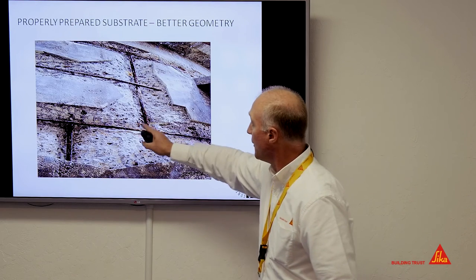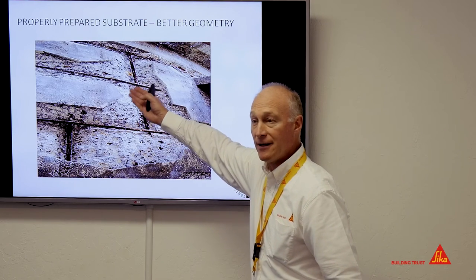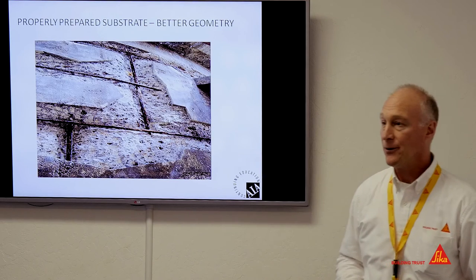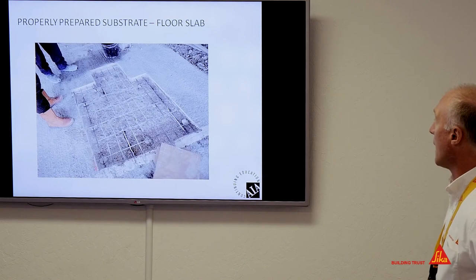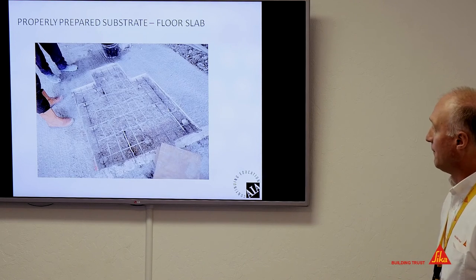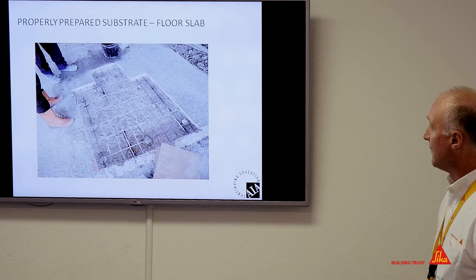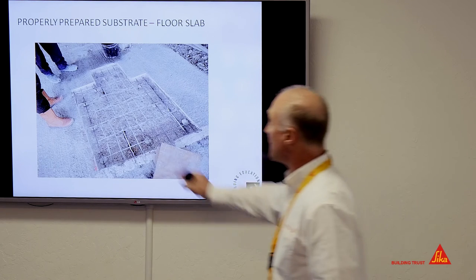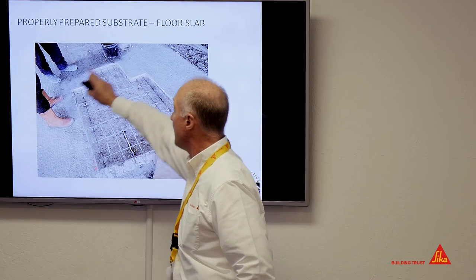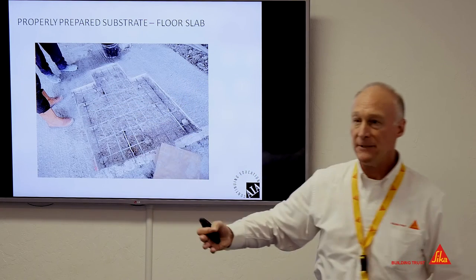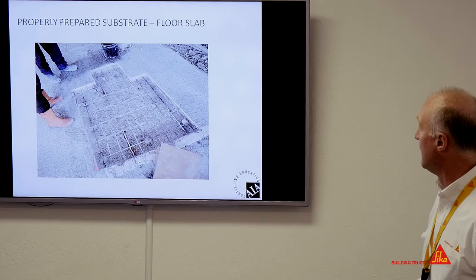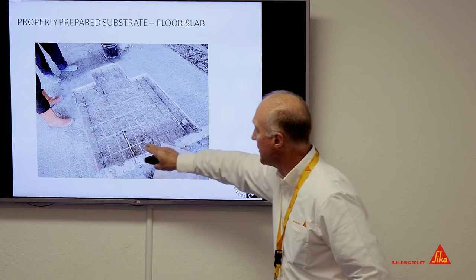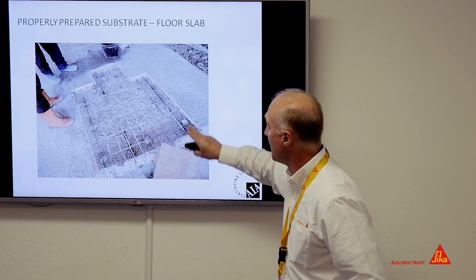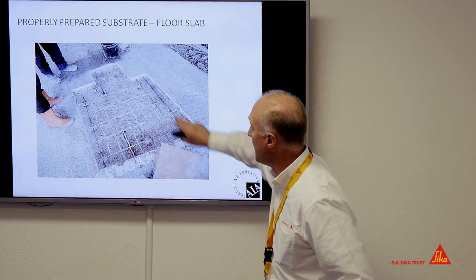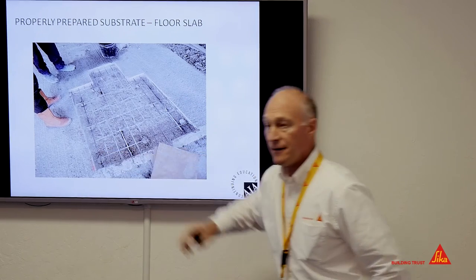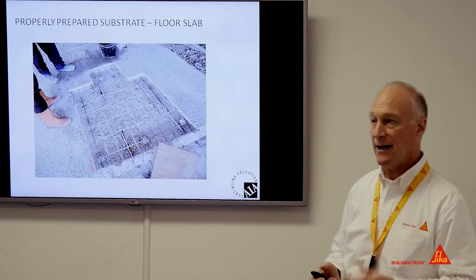The reason they're doing this is to chip out around the bar, so they're really doing what they're being told to do. This is a very nice repair that's been cut out, very simple geometry. Even this, I'm fine with. I don't think you have to take it out to there, but some consultants may require that. In here, they've put some anodes. These anodes are intended to protect the steel out here, this incipient anode, and try to prevent that from occurring.